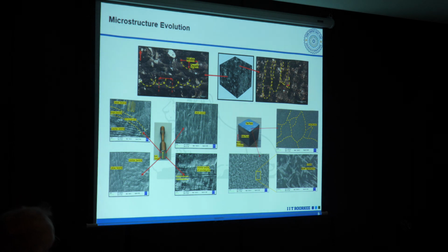Then a cube of 10 by 10 by 10 was also printed, and we polished it and observed the melt pool boundary. The main focus of this presentation is to validate this, and we also did the fatigue analysis in that case. The initial microstructure is cellular and columnar dendritic near the melt pool, and we also observed a needle-like structure, which is the delta phase.